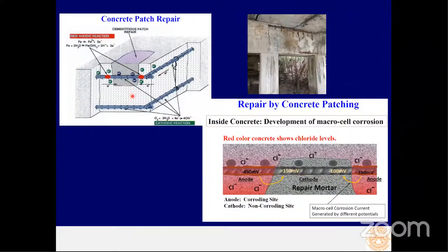However, after some research and knowledge transferred from experts, concrete patching is not a good solution anymore. Because as you can see, after we remove the concrete from the damaged area, we clean the reinforcement and coat it with epoxy in this area, and we do the patching with regular concrete. That's going to form macrocell corrosion. The existing reinforcement that has some minor corrosion will turn into the anode, and after that, the corrosion is going to propagate more in the surrounding area. So the repair work with this method doesn't work anymore.